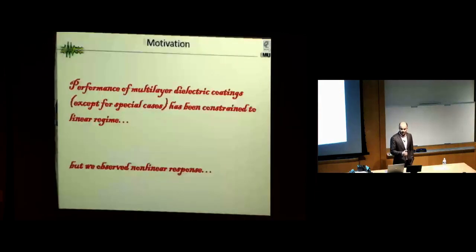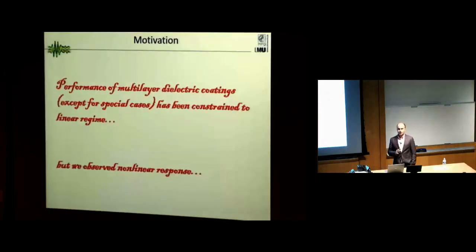Actually, when I spoke before about multilayer structures, usually we consider all layers as linear, in the linear regime. But when we go to the femtosecond regime, the pulse intensity is so high that our layers, which usually are like glass and have almost no nonlinearity, behave like nonlinear materials. And here I will show how the mirrors behave like nonlinear elements.